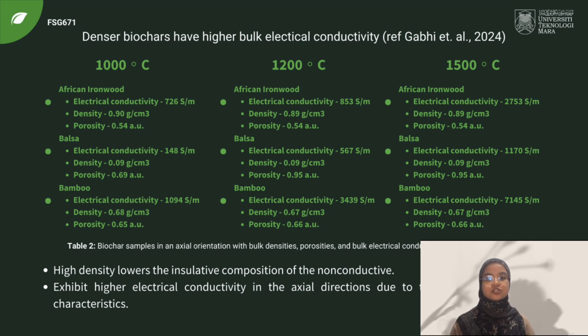Although biochar is naturally porous, similar to its biomass precursor, electric conductivity of monolithic biochar is controlled by electrons that only pass through the rigid carbon matrix. As a result, denser biochar should have higher bulk electrical conductivity because their raised density lowers the insulative composition of their non-conductive air-filled holes in the main structure.